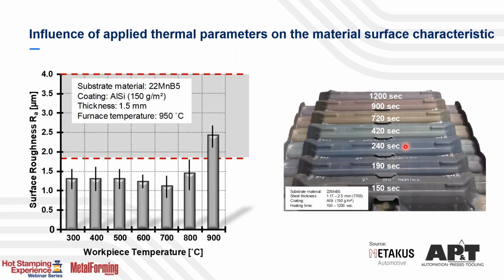On the next slide, you can see the influence of the final temperature that you use, that you reach inside the furnace, on the surface roughness, which is of course a requirement for the final paint job that goes on the parts. And you see, depending on the workpiece temperature, surface roughness is changing heavily. And where we want to end up is basically in this window here, between 1.8 and 4 microns in surface roughness.